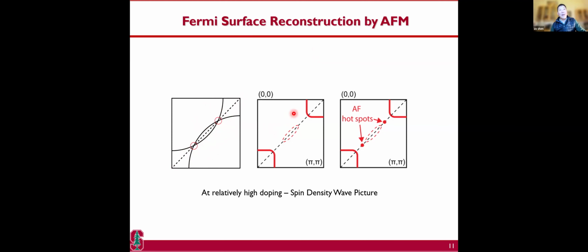Normally, you say, okay, if I have a starting point like this and I further develop superconductivity, you would think that superconductivity should happen on top of the reconstructed Fermi surface. Indeed, in CDW systems such as niobium diselenide, the superconductivity happens on the reconstructed Fermi surface. What I'm going to tell you is that in this case, the maximum superconductivity happens in a region that has the maximum gap. Maximum superconductivity happens in the hotspot.